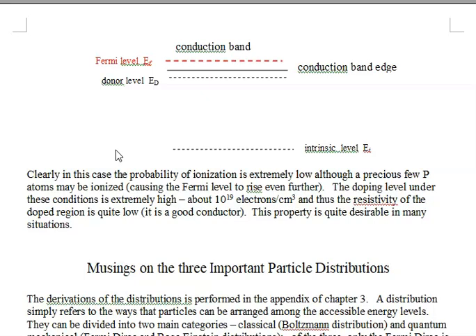So I asked the question, do we really need an hour? Now you'd think that the answer would be obvious. Yeah, we need an hour because it has to be degenerately doped. But we don't know that it needs an hour, because let's say it needs a half hour to get into the same level. What happens to that extra half hour? Well, the probability of ionization is essentially 0. It's extremely small. So we've just wasted a half hour of ion implantation time. We've done nothing but introduce phosphorus atoms which are not being ionized. This is not good at all. It's a huge waste of time, and it's potentially destructive to the lattice.